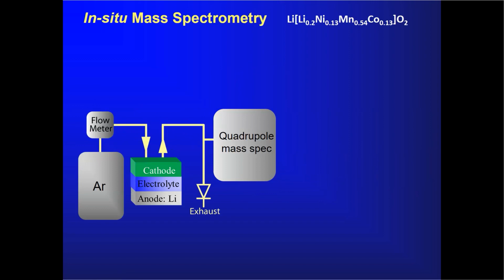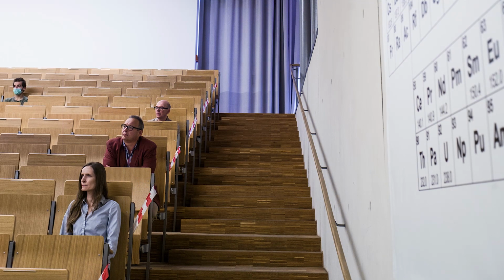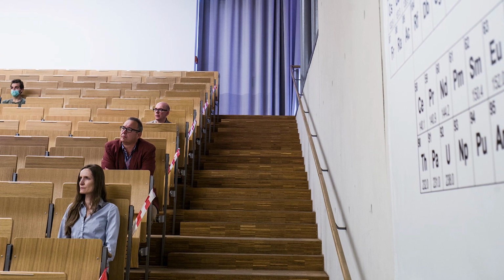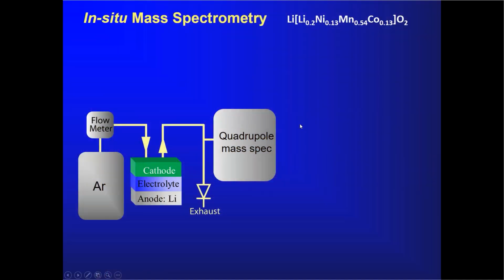So let me just first of all show you something on the oxygen loss question, because it's interesting that when these materials were first discovered more than 20 years ago, the original explanation for this extra capacity was that we were simply losing molecular oxygen, and then after that, reduction was involved, reduction of the transition metal ions and then conventional transition metal redox. And what you'll see here is that there is some oxygen loss, as I touched on earlier, but it's actually only a small part of the story.